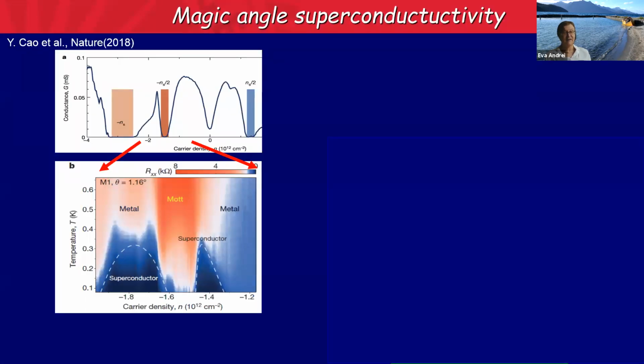And then in 2018, the MIT group announced this spectacular result that when you go around a filling of -2 holes per band, 2 holes per moire cell, you have an insulator, and when we go nearby, you see superconductivity kick in, and it forms a superconducting dome. Notice this temperature scale here is about 0.4 Kelvin, nothing to write home about.